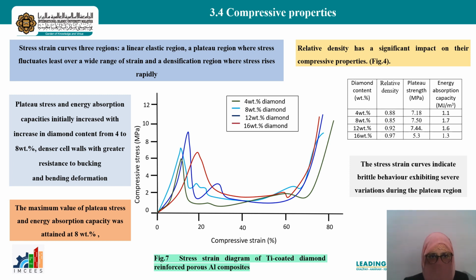The plateau stress and the energy absorption capacities of these composites have been observed to be increasing only up to 8% because of the presence of denser walls with greater resistance to buckling and bending deformation. However, it decreased with increase in the content, and the relative density had a significant impact on compressive properties. Further, the stress-strain curves also indicate brittle behavior, exhibiting severe variation during the plateau region.